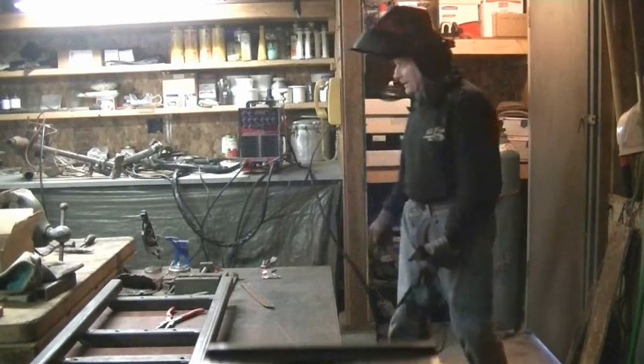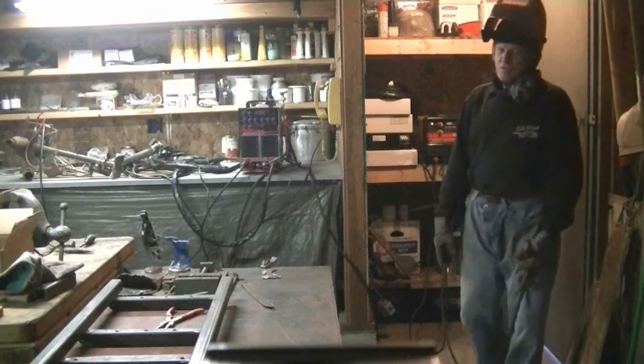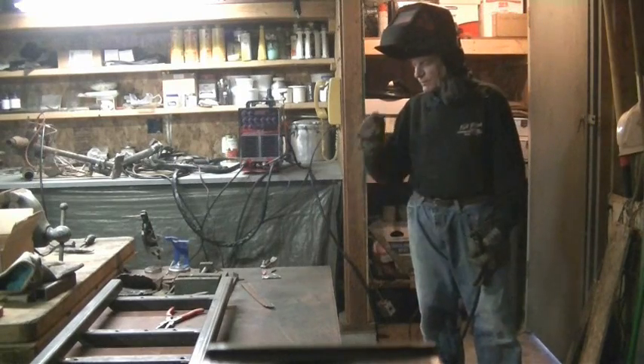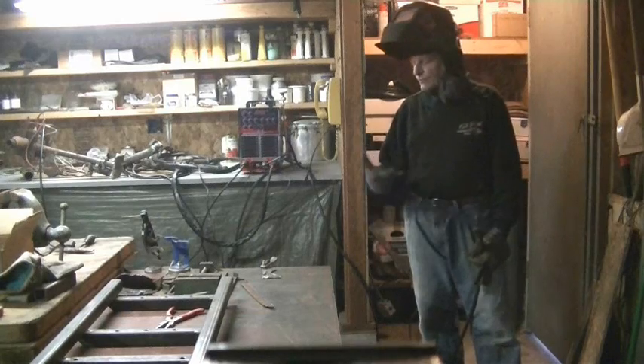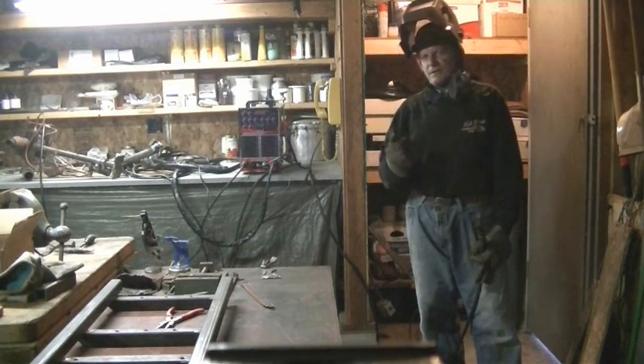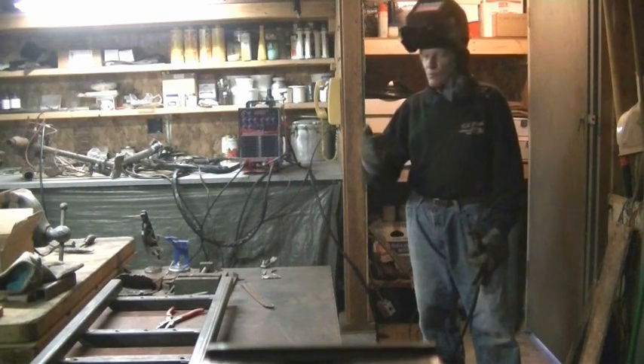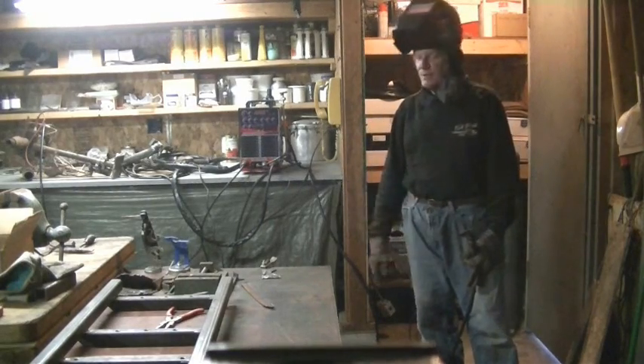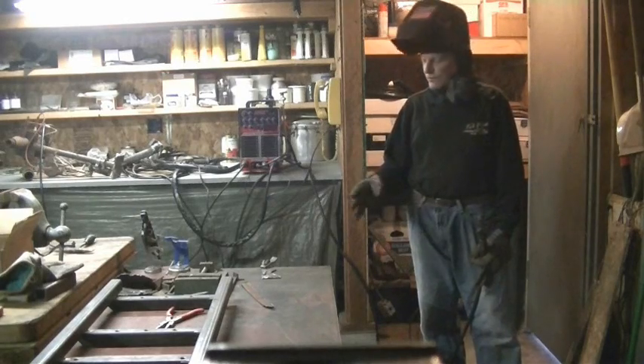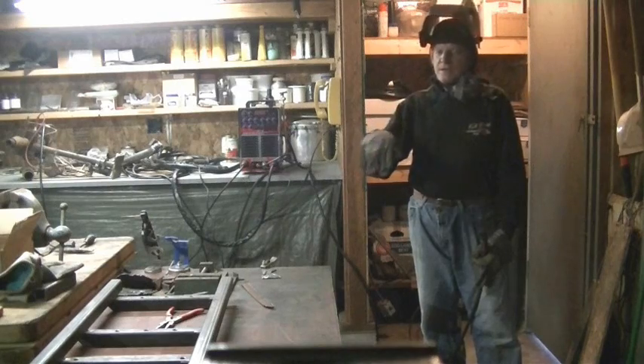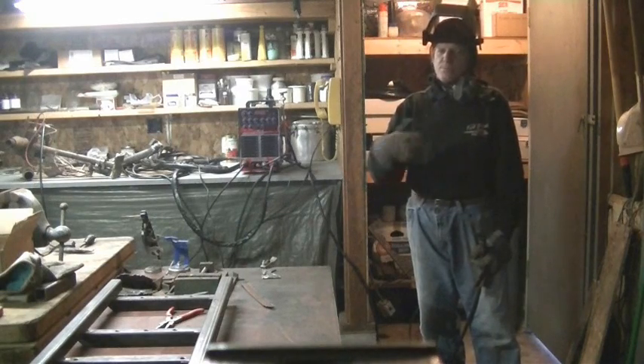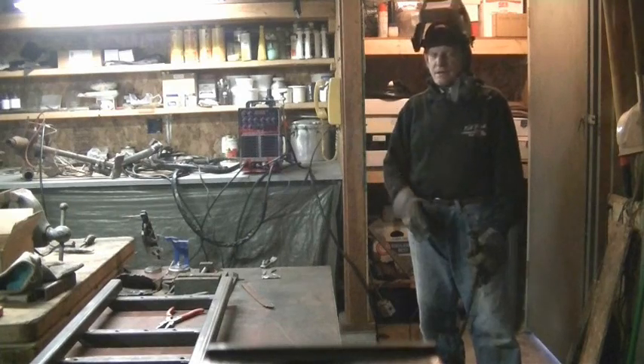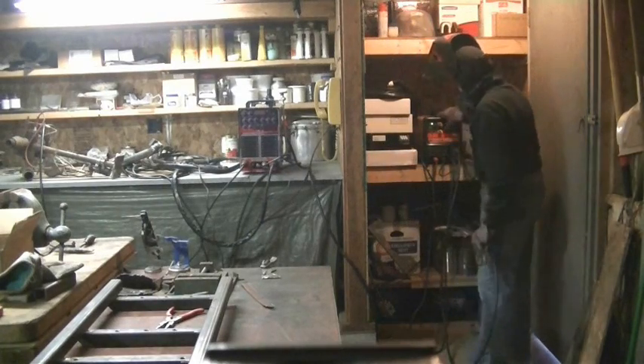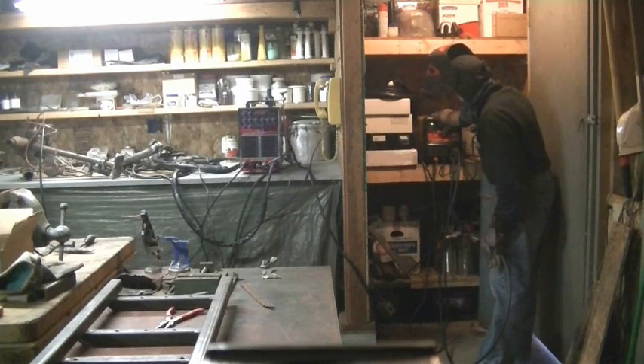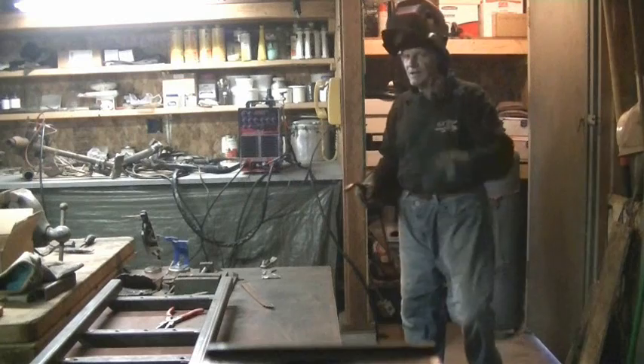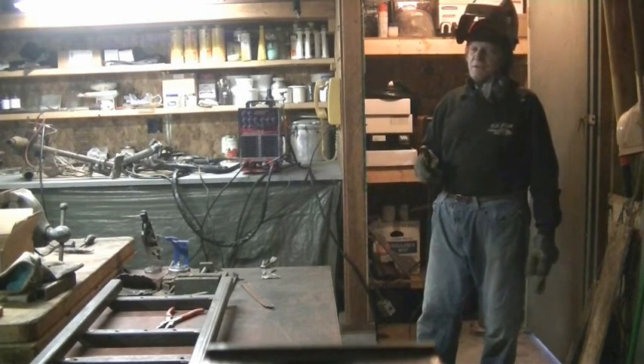Now, the first weld I had too low a voltage and too high wire feed speed, so it was sputtering along, making a really tall, bad weld. Once I cranked the voltage up and the wire feed speed back down, then it started making a pretty good weld. You can hear the difference. In the first one it was sputtering, and then in the second one it sounded more like bacon frying, or a steady frying kind of a sound. So try that one more time and then get the apprentice in here now that I've got it dialed in, and she can give it a try.